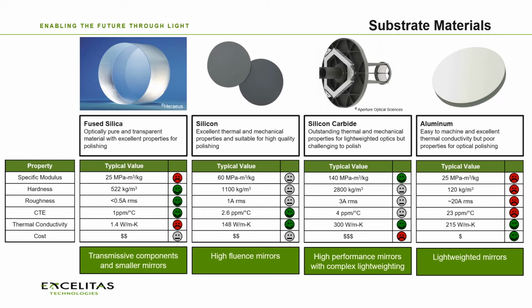It's usually not used in larger spherical, aspherical optics, where the density, the weight, and the stiffness can start to be an issue. Its specific modulus, or the relationship between its stiffness and its density, is not really favorable for making light-weighted optics compared to some of the other materials. Its thermal conductivity is also quite poor, but its thermal expansion coefficient is quite favorable, which means that not only is it very thermally stable in various environments, but it also lends itself well to stress compensating coatings, which typically depend on the thermal expansion coefficient of the substrate material.